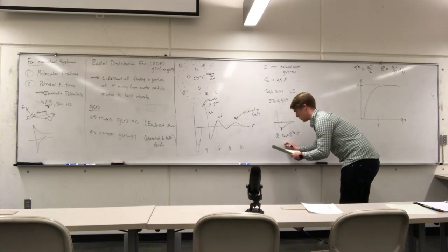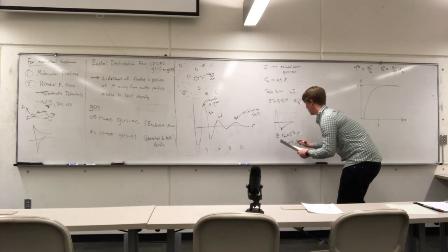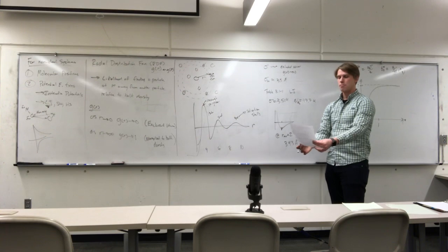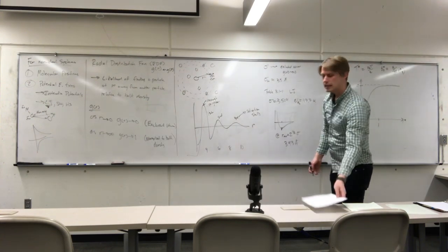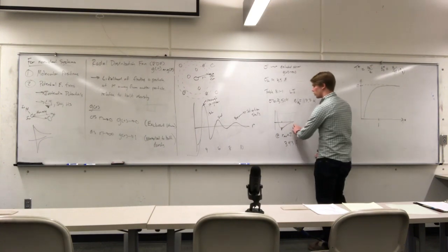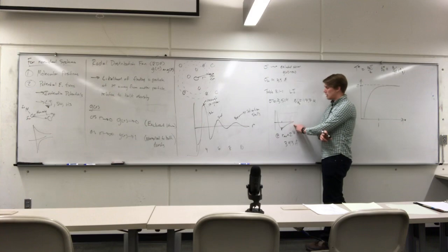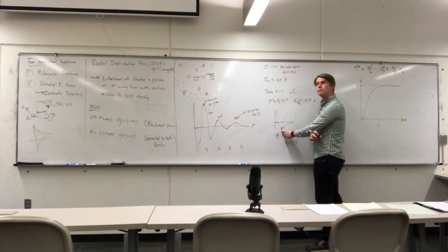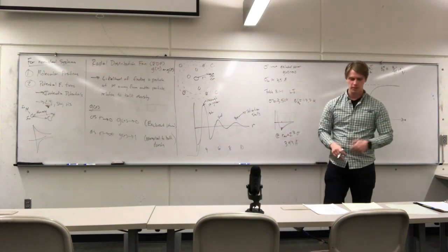And so for argon, that's what we're talking about, it is 3.93 angstroms. And so if we look at our chart here, I would say 3.93 seems pretty good as the minimum separation distance. So that means most of the argon particles, if the Lennard-Jones model is correct, right, this is just a model, most of the argons want to sit in that spot. So if we were to expand it, we would expect it to cool down, as a throwback to the last class.